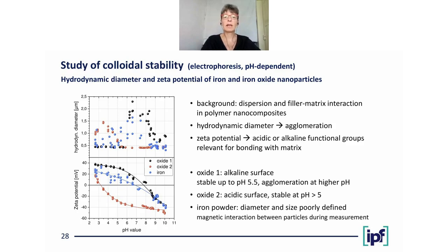For the iron powder, it was a bit more difficult. As you can see here, neither the zeta potential nor the hydrodynamic diameters are well defined. The problem was that we had magnetic interactions between the particles during the measurement that really disturbed the measurement.